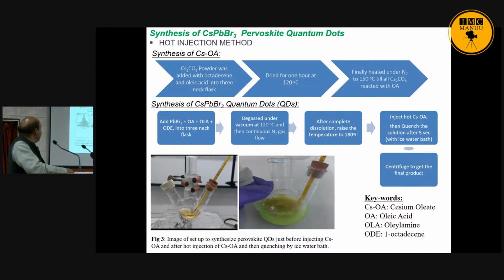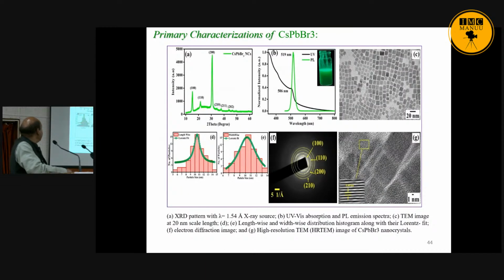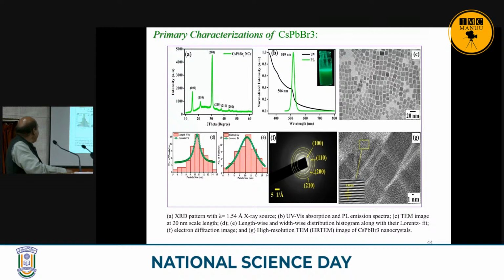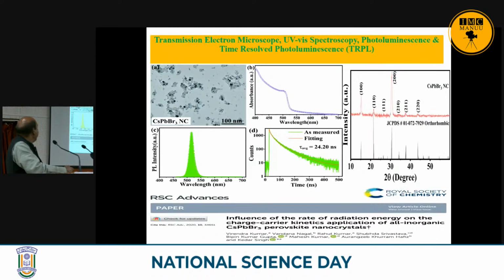Just I want to show you some XRD. This is coming very good XRD. This is the UV spectra. You are able to get this peak here. This is the quantum confinement. PL spectra is very sharp. PL spectra is coming here. Then you can say the size is about 10 or 11 nanometer. It is also showing a very crystalline size, and the size is coming here. This is some gap here. Okay.